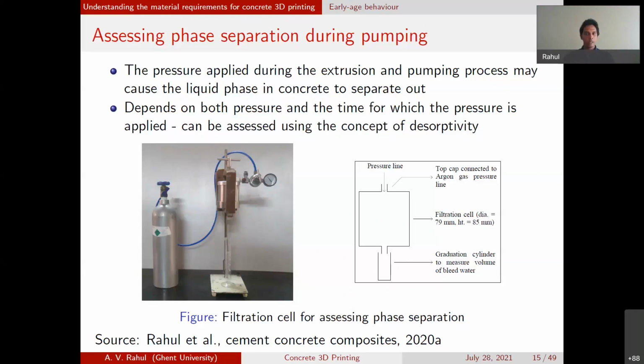One way we can do that is by using an experimental setup which was used in my PhD, shown here. We take a small sample of the concrete and put it in this setup, and a filter is placed at the bottom. The grain size of the filter is around 2 microns, so all the granular materials are left behind and only the water can pass through the filter. Then compressed air is used to apply pressure on the top, and we see how much water is coming out at different time intervals. Using the column of water that forms at different time intervals, a parameter called desorptivity can be obtained, which can be related to phase separation.